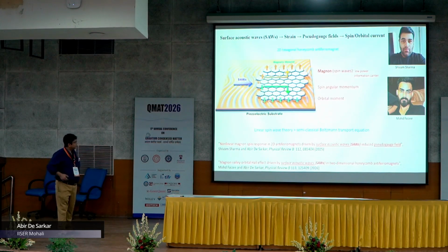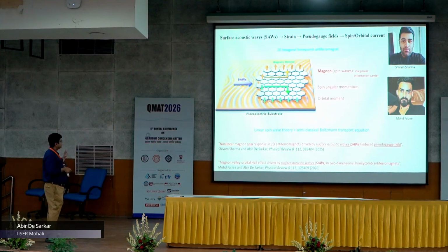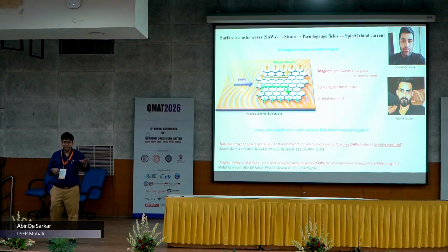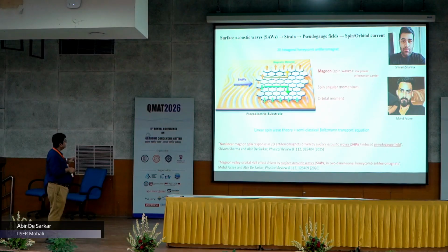And this is an interesting application of piezoelectricity which we have demonstrated in these two articles. So this piezoelectric substrate would generate surface acoustic waves which would induce a strain in this two-dimensional hexagonal honeycomb antiferromagnetic material which is supported on the piezoelectric substrate, and this strain, experienced by this 2D hexagonal honeycomb antiferromagnet, would generate pseudo gauge fields, and the pseudo gauge fields can then drive the magnons through this 2D hexagonal honeycomb antiferromagnetic material.